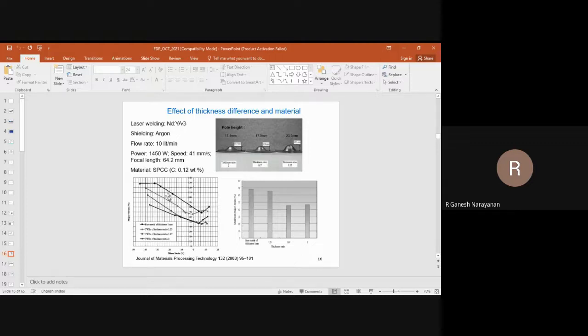See, you are converting a base sheet of SPCC material of 1 mm thickness to a welded sheet, with the same material but with thickness ratio of 1.25. So we actually do not want formability reduction, right? Because you want to make a component, then you need this much of window to form. If you reduce the window, you cannot make the component.